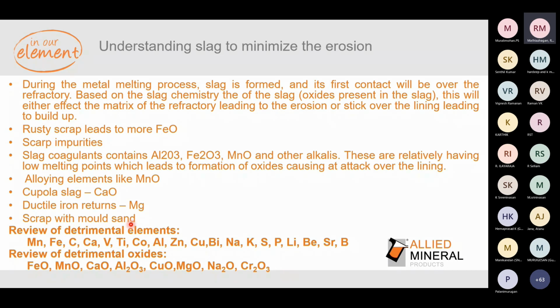So slag is one reason, and understanding slag is important to minimize the erosion. Slag formed during the melting process comes in first contact with the refractory. Based on the chemistry, it has an effect over the lining, either in the form of erosion or in the form of buildup. Slag is due to iron oxide present in the scrap and impurities in the scrap, like cupola slag, which contains CaO, and scrap with mold sand. Deslaggers, which are slag coagulants, also contribute to the erosion, because these contain a lot of elements like MnO, Al2O3, Fe2O3, and other alkalis, which have a low melting point, which in turn leads to the formation of oxides, causing an attack over the lining.